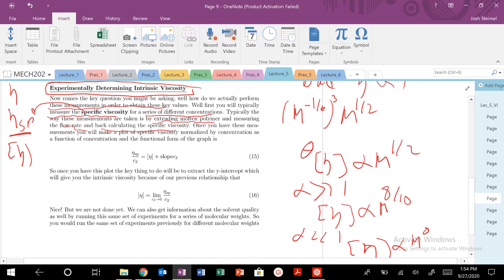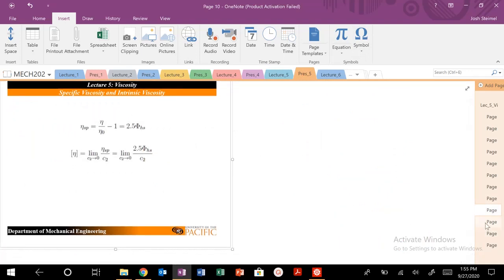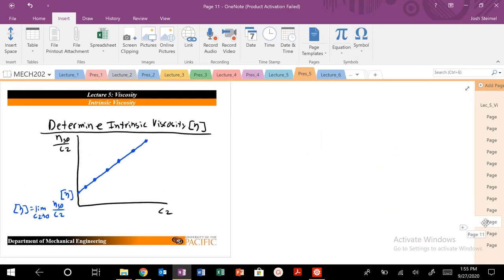Once you have those values, you make a plot of specific viscosity divided by concentration. You'll get a linear slope where the y-intercept is your intrinsic viscosity and your slope is some constant times the concentration. For a series of concentrations, you measure that specific viscosity normalized by your concentration. As concentration increases, your specific viscosity increases, which makes sense. Why does the y-intercept give us the intrinsic viscosity?